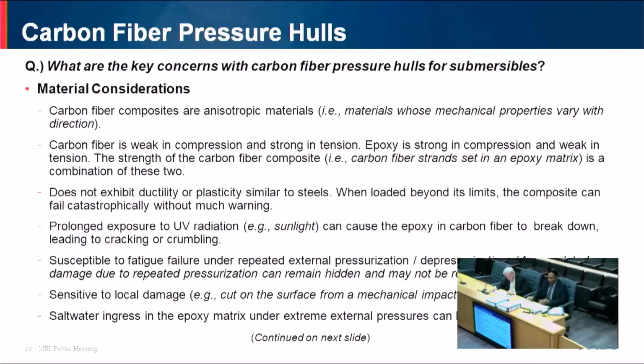Okay? So typically what we have seen is anytime you go below a depth of 1,000 meters seawater, or 3,280 feet seawater, the shape of the pressure hull is spherical. We have not seen cylindrical pressure hulls being used beyond a depth of 1,000 meters seawater. The reason is a spherical pressure hull is the best shape for resisting external pressure. The stresses are evenly distributed around the hull.